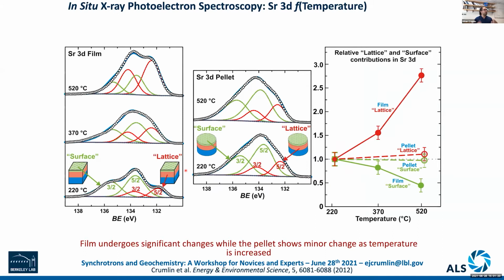So we see strontium, for example, and we compare the strontium signal from the film to the pellet. We see that the pellet, as we increase the temperature, changes very little. However, we see just from the high level standpoint of how the spectra, let's just take the shape of these curves, as they change as you increase temperature, there's a significant increase in quantity of strontium within the thin film. So this means we effectively are seeing a large amount of enrichment or segregation of strontium at the surface, especially in comparison to that of the bulk pellet. So the thin film has this property of enhancing and enrichment and segregation that's there.